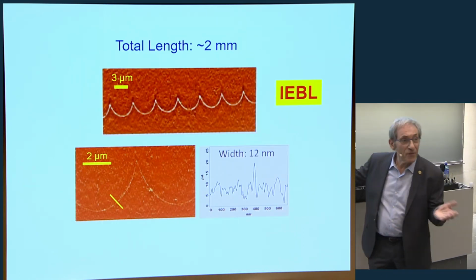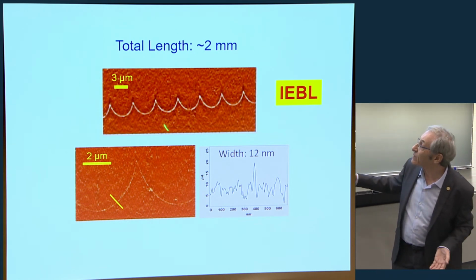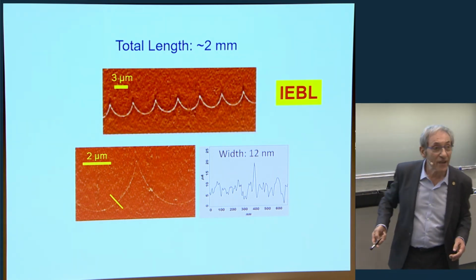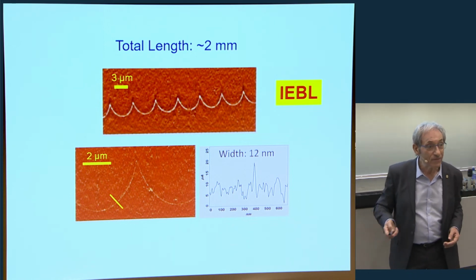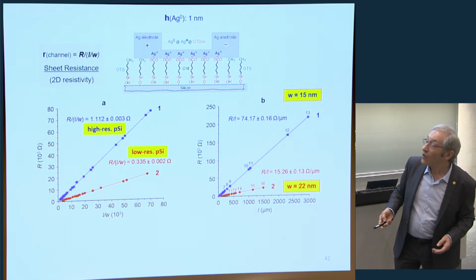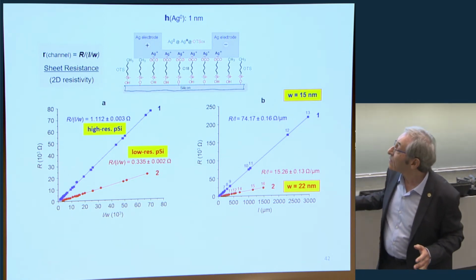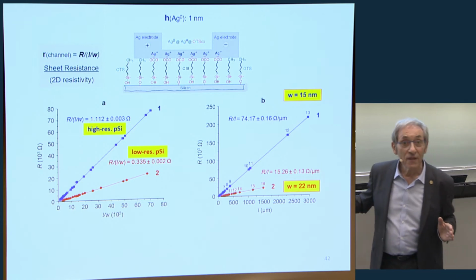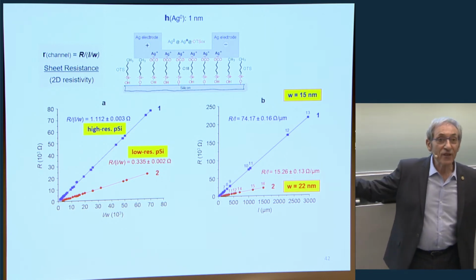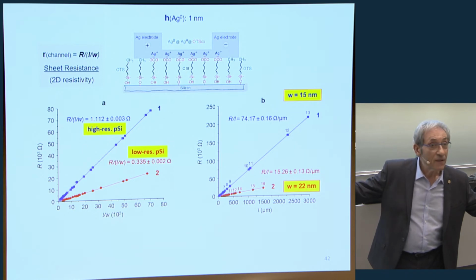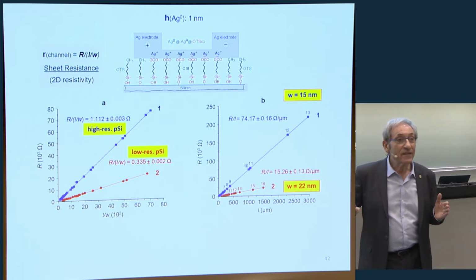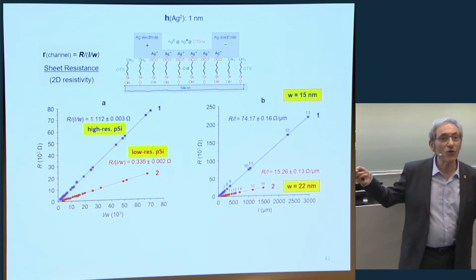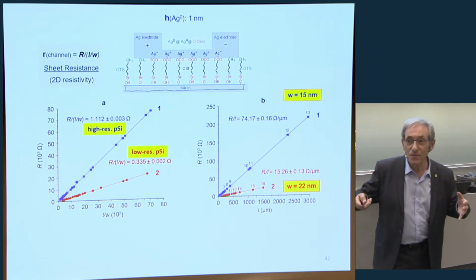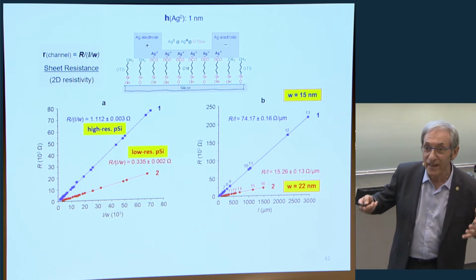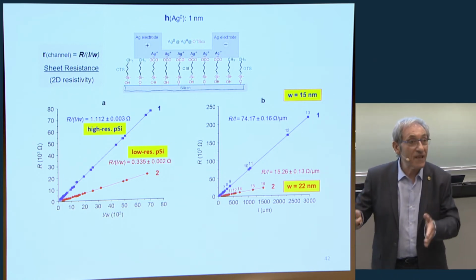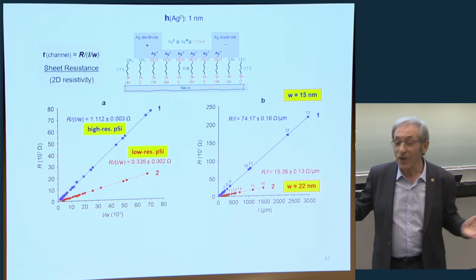Okay, this is another, we can do any shape. So this is total length 2 millimeter, and the width here is of the order of 12 nanometer according to AFM. This is also a very good conductor. Okay, so now what we are doing, we are placing electrodes, and we can place electrodes at different distances from one another. And what is interesting, these are extremely robust structures. We can remove the electrodes by dissolving them in strong nitric acid, and place new electrodes on the same wire at different distances and see what happens.